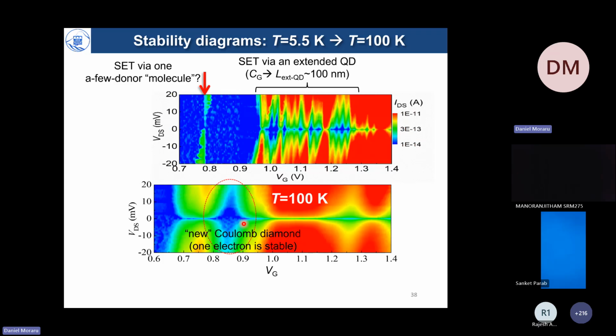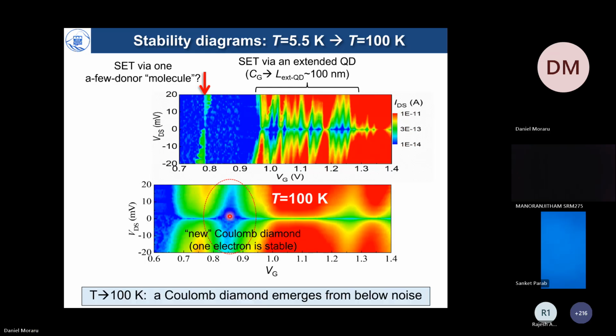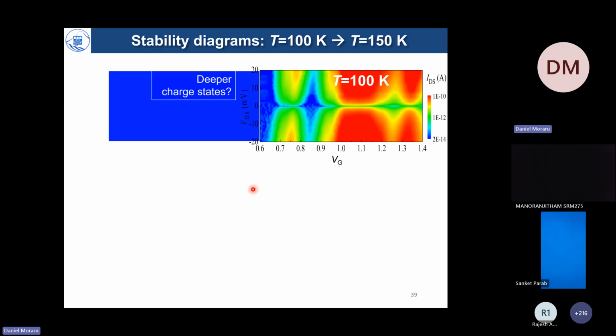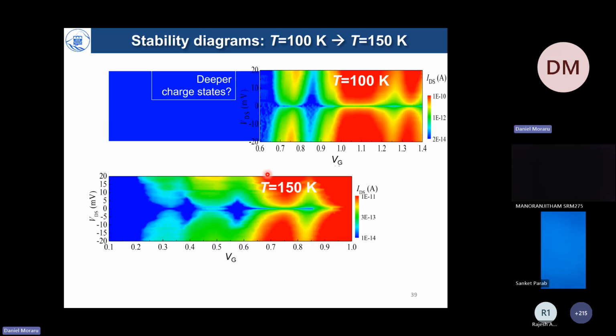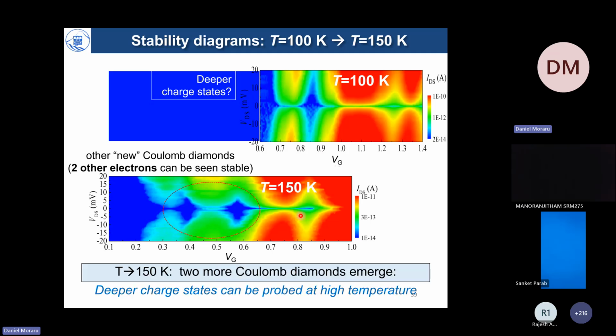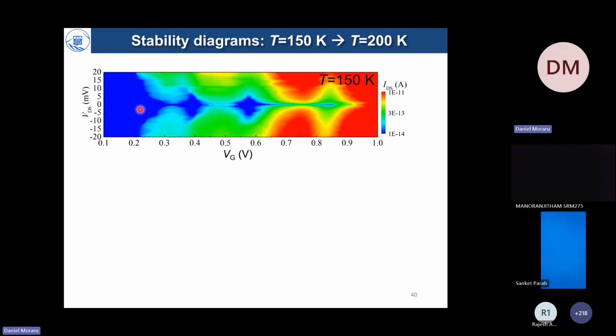And this means that we are actually able to see at mid-temperature range that one electron can be stably trapped in this zone without contributing to current. So it's already a big achievement, but we were curious if we really are dealing with a molecule formed by a few donors. In that case, we should have deeper charge states. If we raise the temperature further to 150 Kelvin, we indeed observed two more Coulomb diamonds at deeper charge states. And that means two more electrons can be finally observed by raising the temperature. And the third electron is also barely seen. So midway to room temperature, at 150 Kelvin, we can actually read the operation of this device in the following way. As we increase the gate voltage from, let's say, 0.2, 0.3, up to 0.4, exactly one electron can be added into the channel. And if you switch the voltage a little further, you can get even further addition.